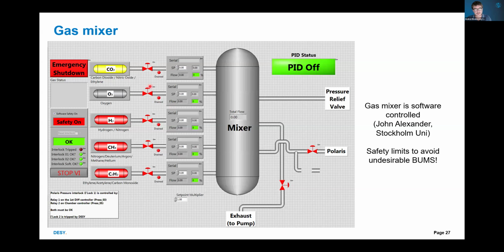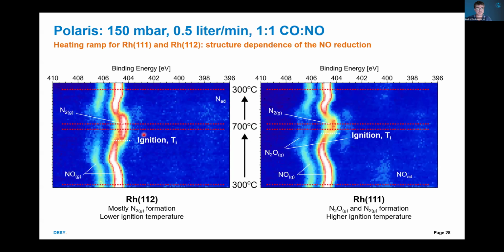And this is a bit complicated experiment. So if you want to apply for a beam time, you have to collaborate with Stockholm University, because it's not so user-friendly, but it's a very productive machine. You can study catalysis, for example, a rhodium crystal with 2 different orientations. You expose it to a CO-NO mixture at different temperatures, and you can see that the 111 surface has a higher ignition temperature, for example.